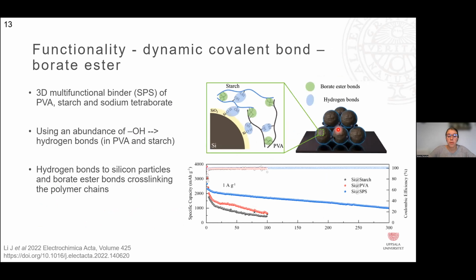If we look at a new example published in September last year, they also use a 3D multifunctional network based on PVA, starch, and sodium tetraborate. And this system is utilizing the OH groups in PVA for an increased adhesion to the silicon particles and dynamic covalent bonds in the form of borate ester here to cross-link the polymer system. And this also provides a greater stability in cycling and an increased cycling performance compared to the two binders separately. Also in this paper, as in many of the others, the mass loading is rather low. So it's around 0.4 milligram per square centimeter. So that is something that can be improved further on.